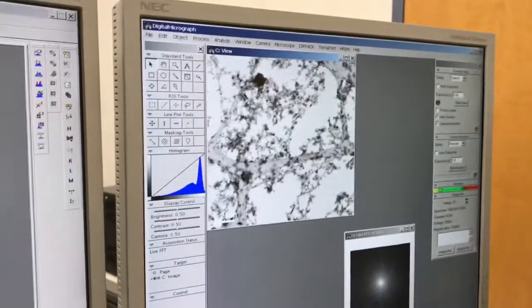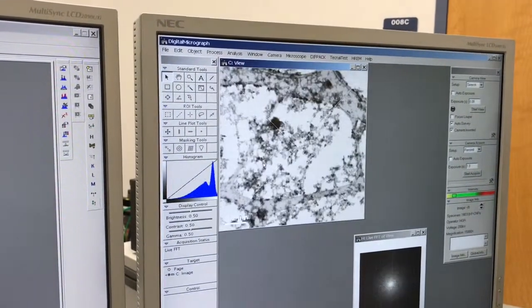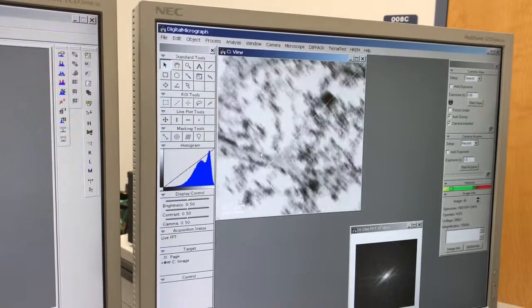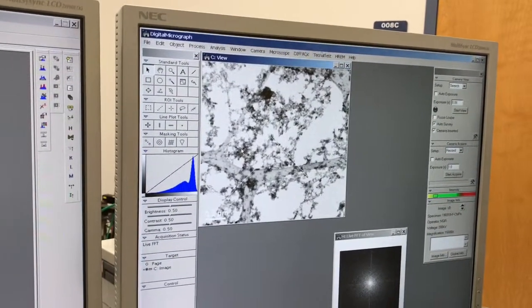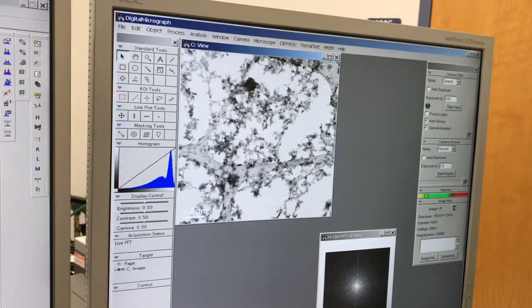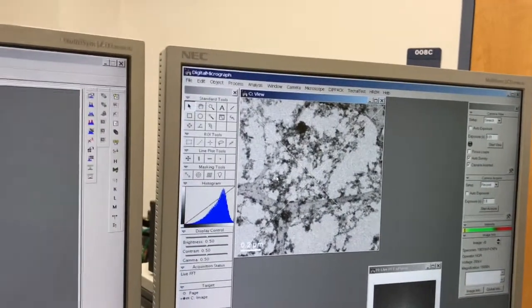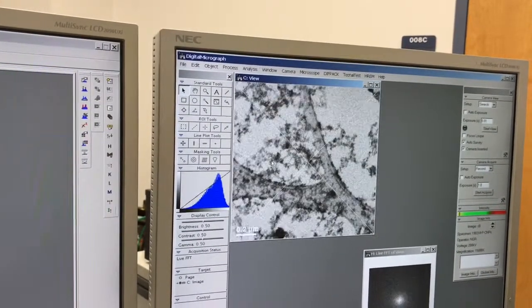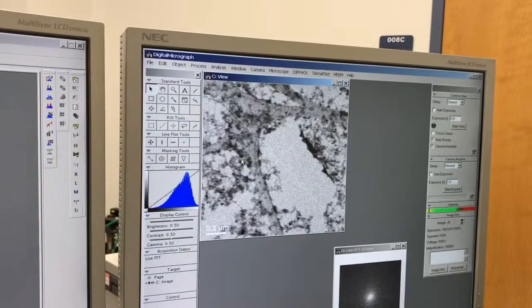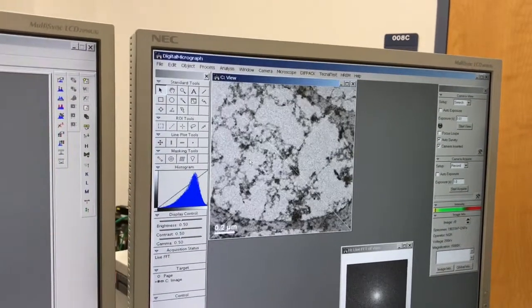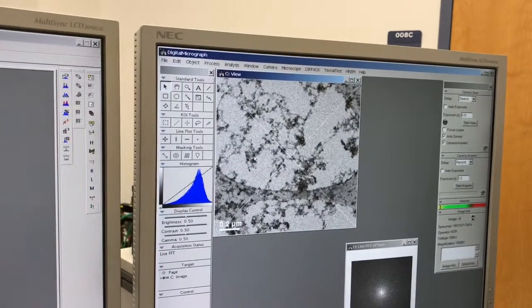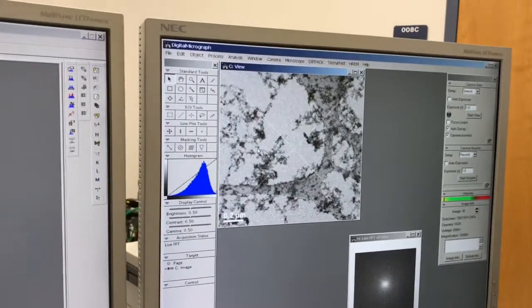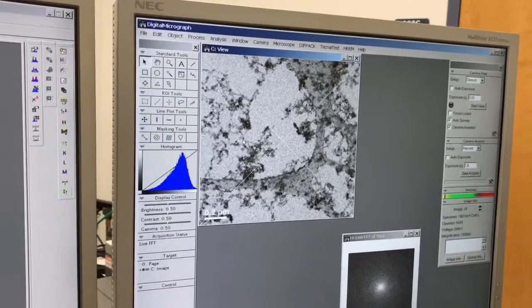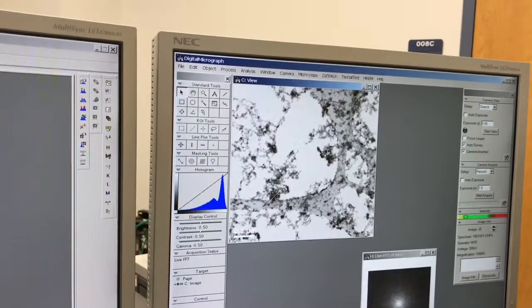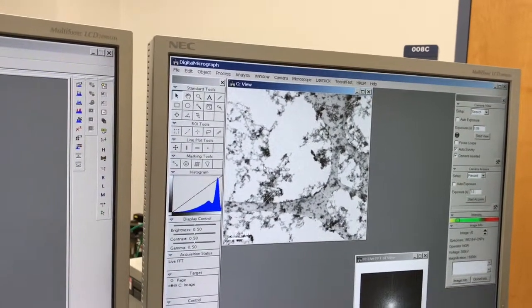But one of the things you can see here, if I go to the joystick, I want to move around. I have a little bit of a lag here because I have a longer exposure time. So if I go back down to 0.01, I do 3 down clicks of the arrow. I have a bad signal to noise ratio, but my camera response is a lot better. So if you're trying to move around quickly and just find an area, it's usually good to use a shorter exposure time. But once you've found your area and you want to actually see it in some meaningful way, you can go back to something higher. Again, I usually use 0.08 as a live exposure time.